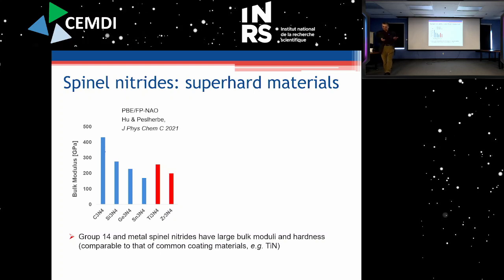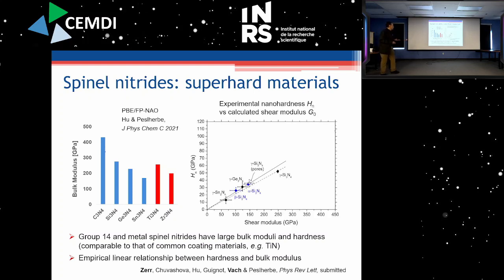So this is what we can calculate from DFT calculations. And what our experimental collaborators in France at Université Paris Nord and École Polytechnique, Andreas Zerr and Holger Vach, are able to measure is the nano hardness, so we call it H. And they could compare the nano hardness measured for all of these phases of different materials to the calculated shear modulus, and they could find an empirical linear relationship between hardness and bulk modulus.